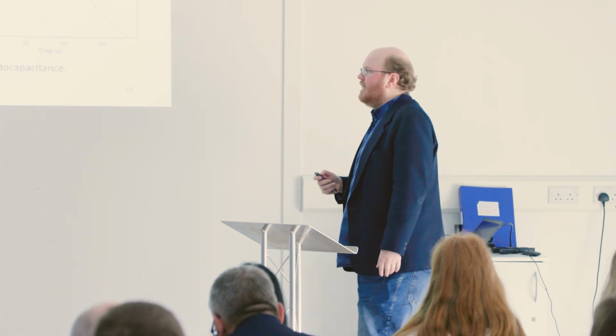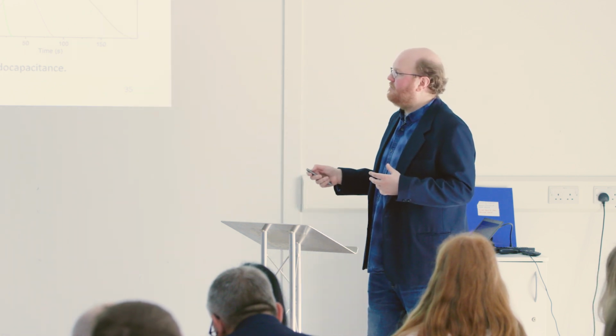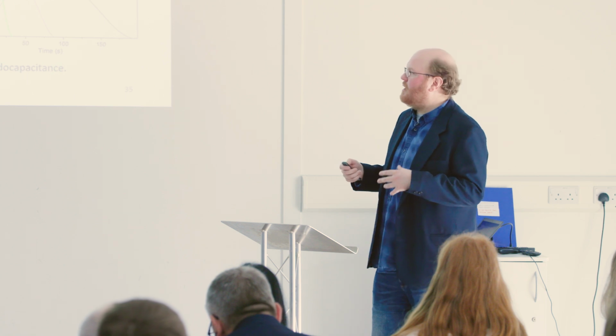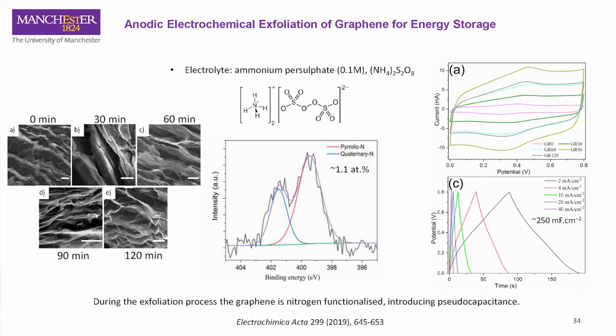So that's an example of how, by modifying the way we think about, say, a supercapacitor or an electrochemical device, we can develop newer technologies that take advantage of what graphene inherently is already giving us. We get added benefits in terms of preventing that restacking, and if we can functionalize the surface with other molecules, we can improve performance as well. So when we do this electrochemical exfoliation in ammonium persulfate, which has this structure, we introduce some nitrogen. We nitrogen functionalize or nitrogen dope the graphene at about 1%, a pretty mild amount of doping.